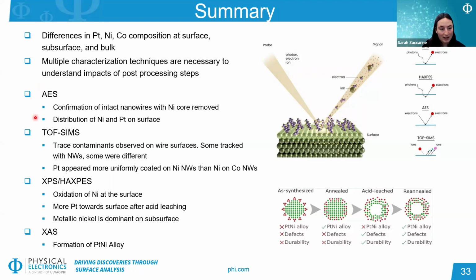We also were able to look at the distribution of nickel and platinum across the sample surface. We saw some small heterogeneities even on individual wires. With the TOF-SIMS data, we looked a little bit more closely at some of the surface contamination. We noticed that some of those species tracked more with the nanowire shape and distribution, but others were different, which told us a little bit about contamination of the wires themselves versus more external contamination.